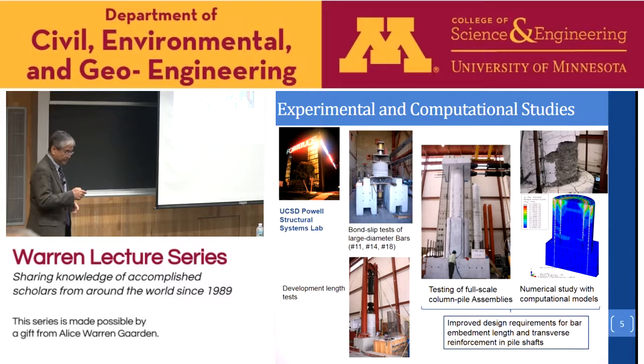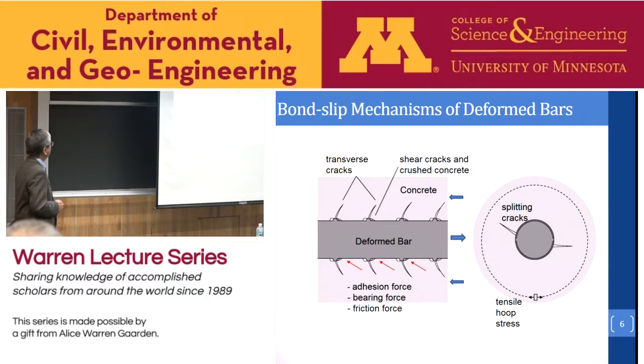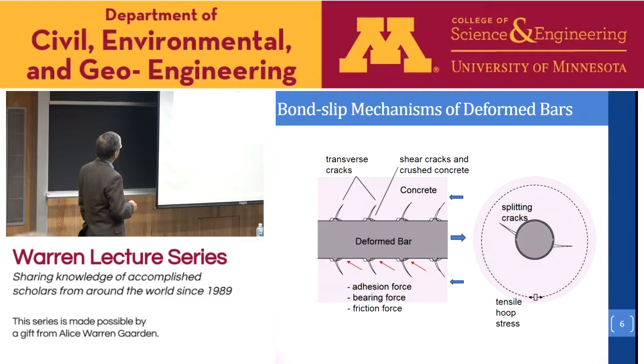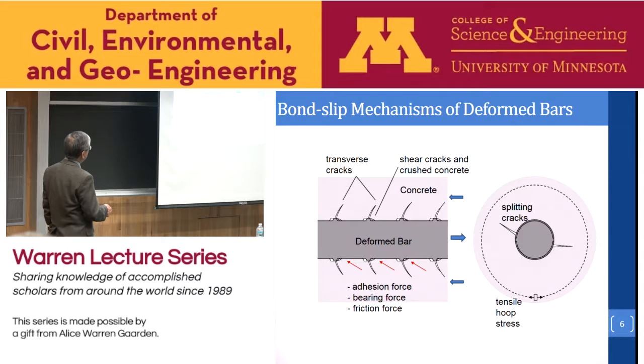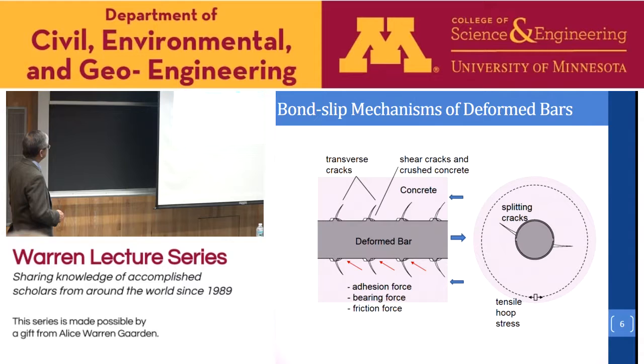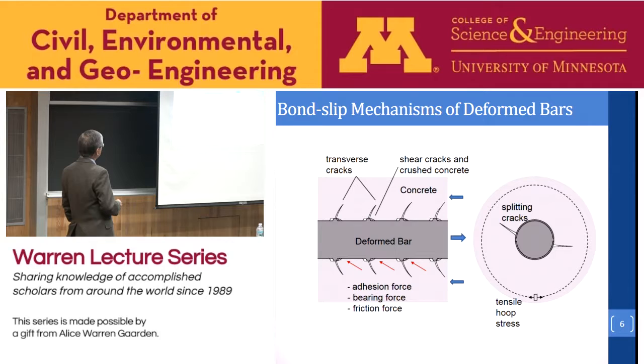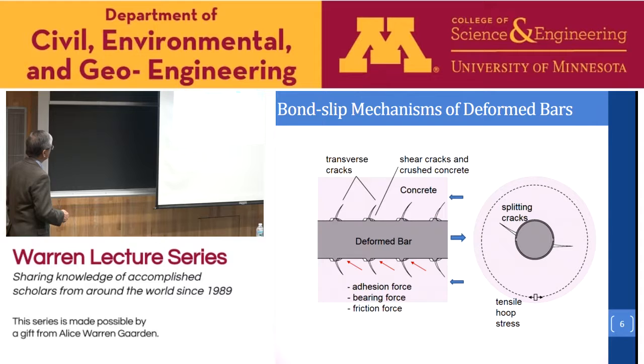So now the anchorage is very much related to the bond slip mechanism of deformed bars. So this just introduced the physical mechanism of bond slip. Imagine that you have a bar embedded in concrete and the bar is pulled in this direction, okay? And normally the resistance to the slip is provided by first some adhesive force between the steel and the concrete, and then the bearing resistance is the bearing of the concrete against the bar ribs, and also the frictional resistance, okay? And the bar is pulled, it could cause crushing and shearing of the concrete in this region, okay?